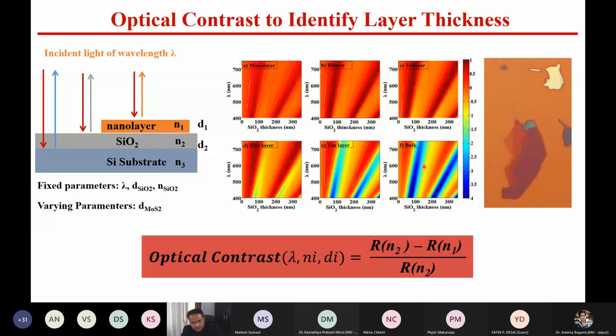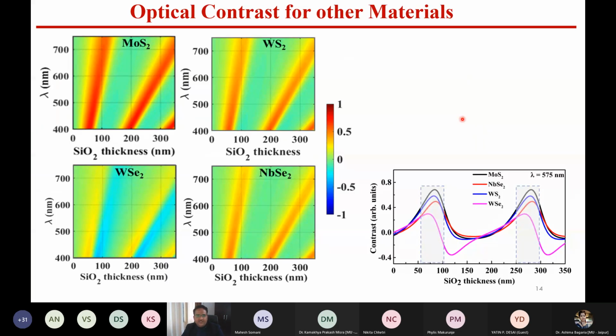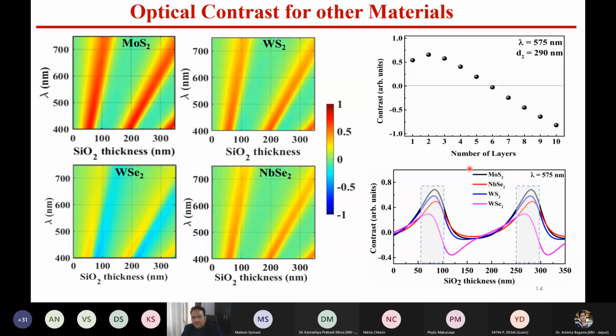So this is for the monolayer of MoS2. This is bilayer, this is trilayer, this is four-layer. These graphs are for the various layers, and the contrast value is shown on the scale here. From here you can estimate where the monolayer is and what is the right silicon oxide thickness. And this is not only for MoS2. One can do these simulations for WS2 as well as WSe2, NbSe2, MoSe2; there are several materials.